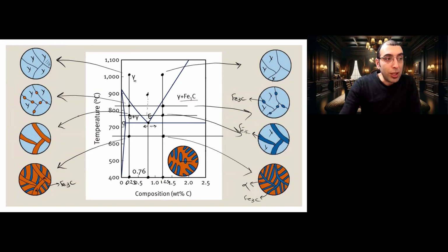But as you're cooling down from this region to that region, only one phase transformation will occur, because this is a unique property of the eutectoid point. You see all these phase formations from austenite for hypo and also for hyper, how many phase changes we have. Here, at the eutectoid point, we have only one phase transformation from austenite, which looks like this or that, directly to this.